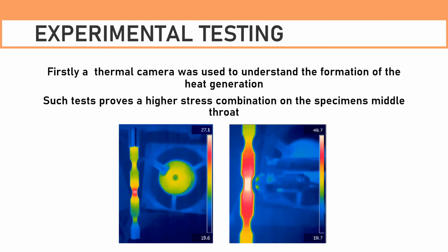After machining the specimen, the thermal analysis test was firstly performed in order to understand if indeed we had a higher stress in the middle throat. Looking at the images and the temperature generation, we can see that indeed the main stress region is in the middle throat.